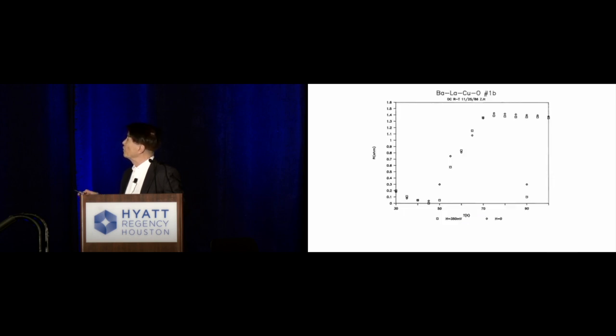In addition, we also looked at some of the mixed phase material. We occasionally observed the Meissner effect up to 70 degrees, but it was not stable and could not be reproduced. So in the back of our minds, we said there's no problem, it must be there, but how can we stabilize it?